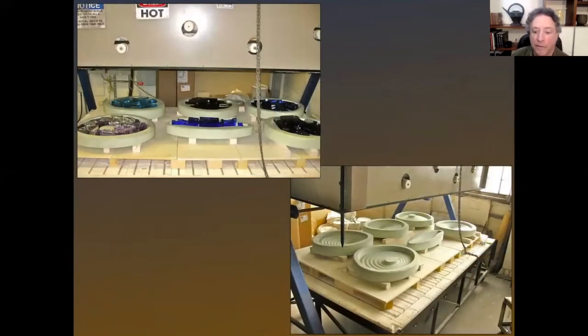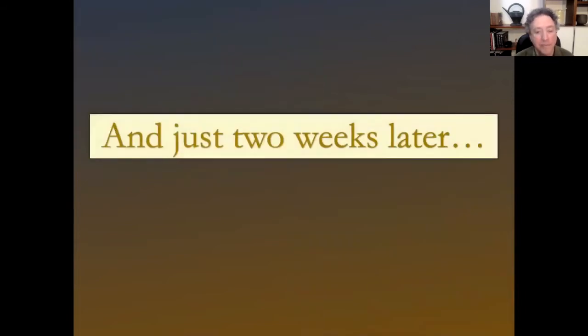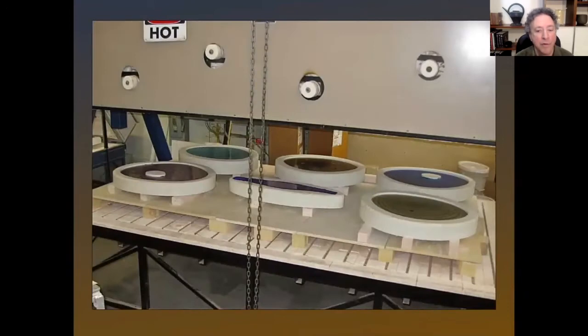So we loaded them into their two massive kilns. These are maybe 15 feet by 9 feet, the biggest I'd ever seen. Loaded them up with about 40 to 45 pounds of glass billets and fired them. And just 2 weeks later, it was Christmas morning. So the thicker the glass is, the longer it takes to anneal. And the annealing times go up geometrically as thickness increases. So the total firing cycle for these was actually about 13 days. And I went home back to Wisconsin and then came back to open the kilns.